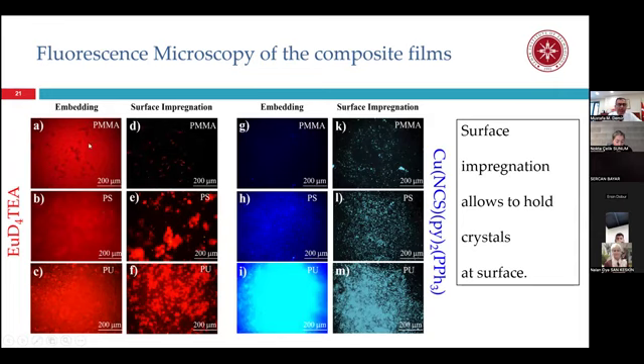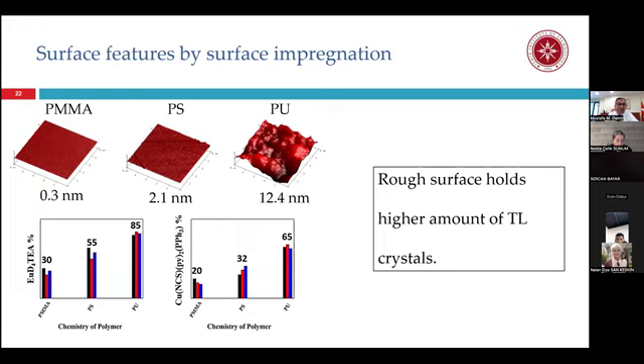In the embedding case, for the red one, for example, you see red emission from every pixel of the image. So the molecules are well dispersed over the polymer volume, but we don't have a triboluminescent signal. For surface impregnation, depending on the concentration, you have different islands, and these red islands indicate the presence of triboluminescent crystals. So surface impregnation allows holding crystals at the surface. Why does polyurethane seem much better? Because it has hydrophilic and hydrophobic domains, and this difference in reaction to humidity creates a porous surface on the structure.